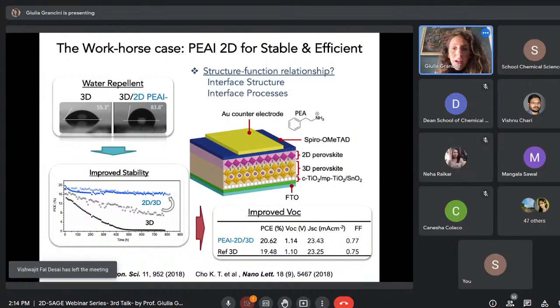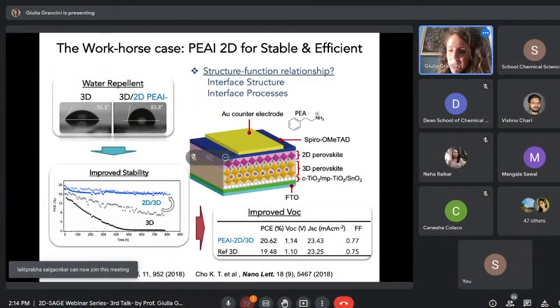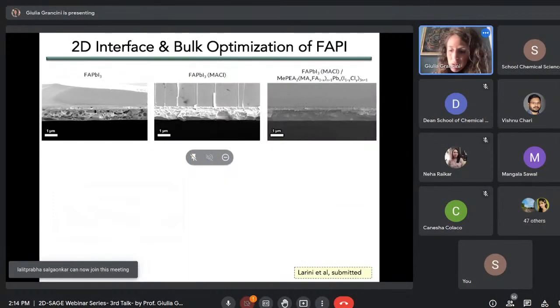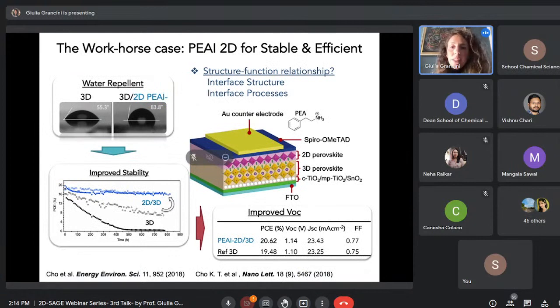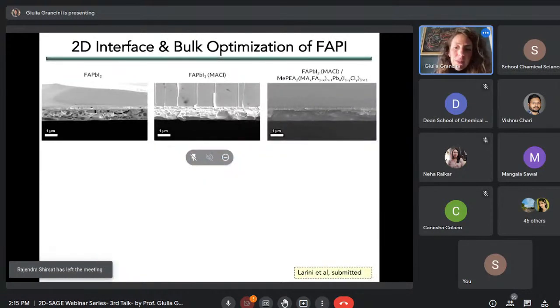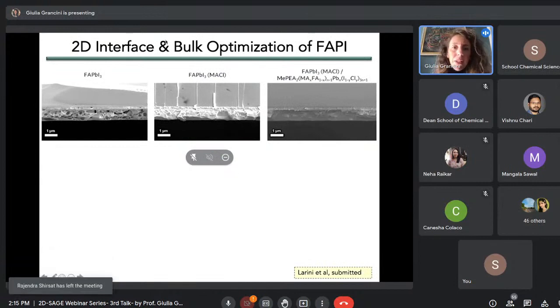Of course, to do that, you really need to optimize the interface structure, the processes, and the materials that you used. Here, I would like to present to you a recent work that is just submitted, where we used FAPI-based perovskites, which is nowadays the most efficient one, that we doped in the bulk with MACl, but importantly, we make a thin layer of 2D perovskites on top of it,